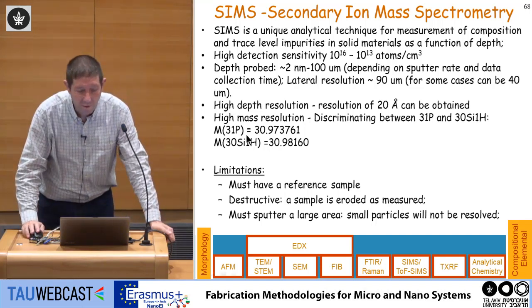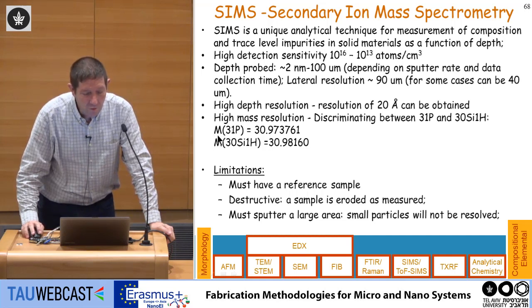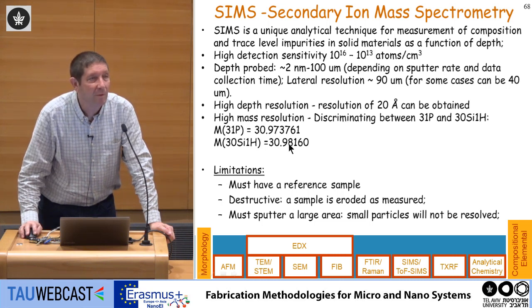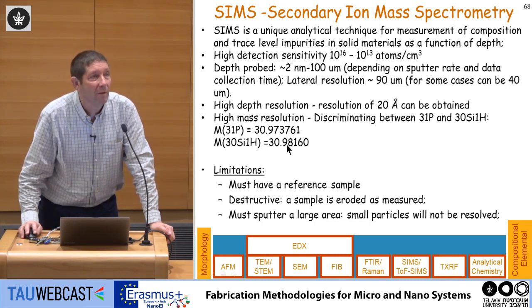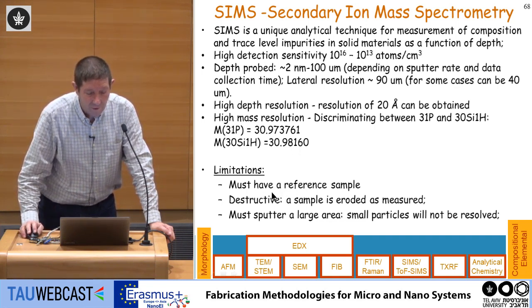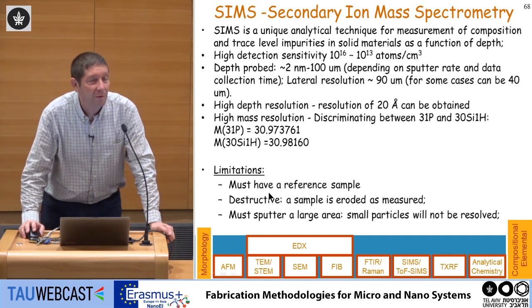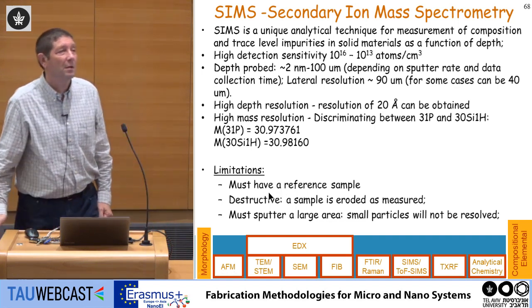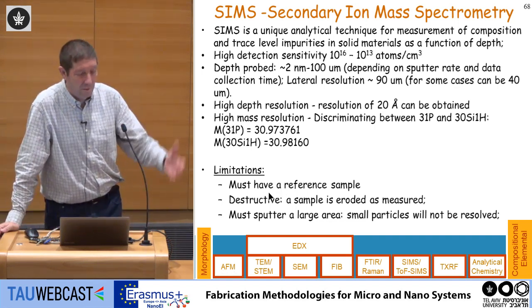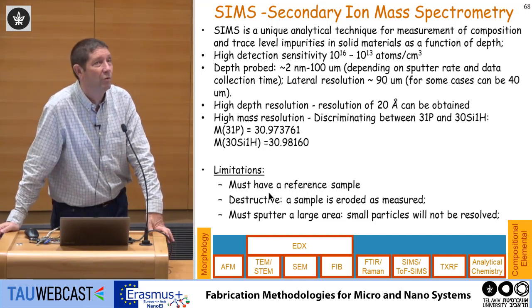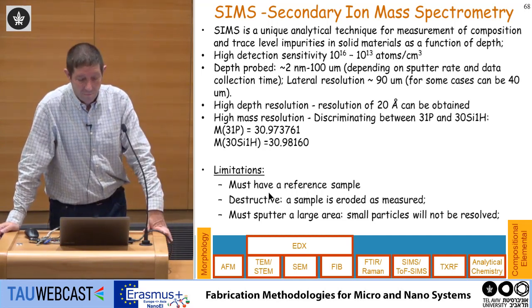There are two techniques that we use today. Because the atomic mass of phosphorus 31 is 30.97 something, and the mass of silicon hydride is 30.98, I can detect between them. A typical, normal SIMS system can see the difference. I need to have a reference sample. It's very critical for this measurement. If I have an unknown composition or a new composition, I need to have some reference.